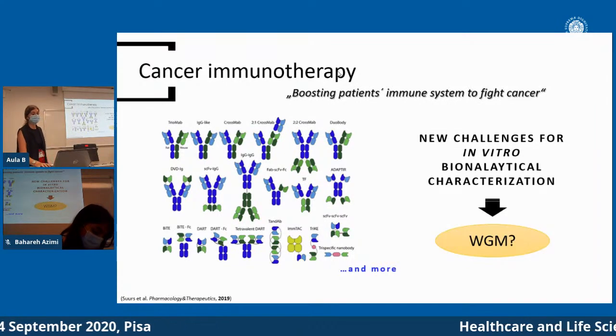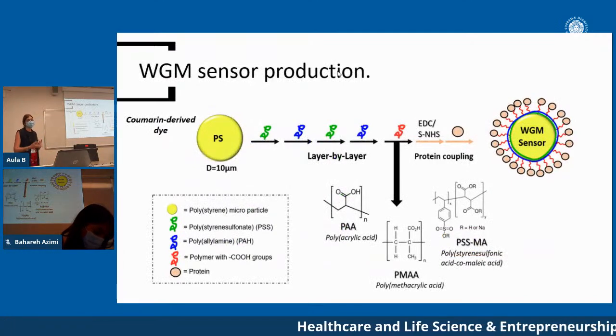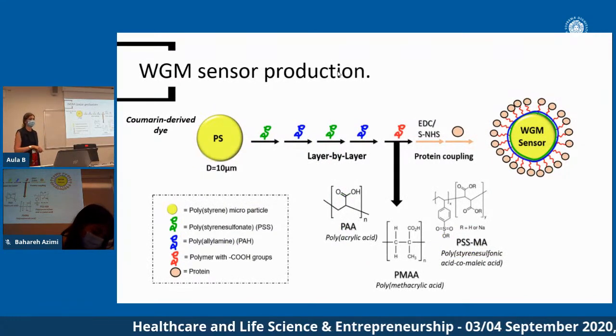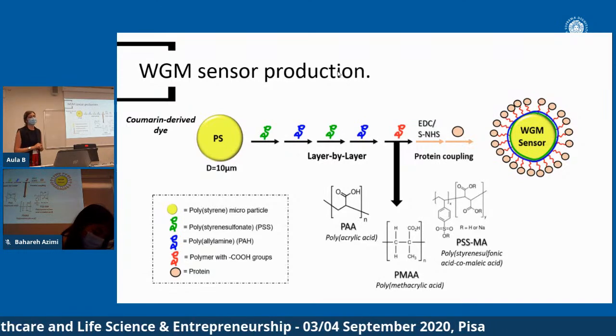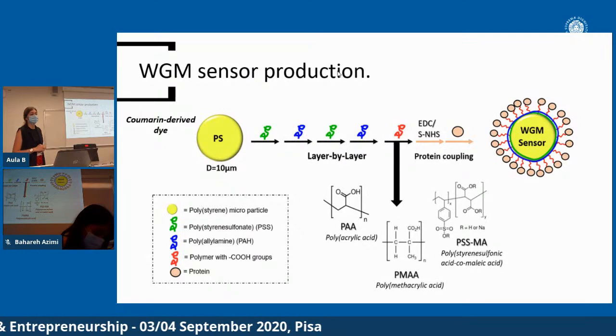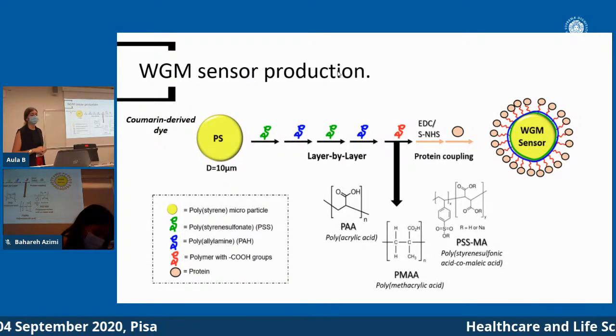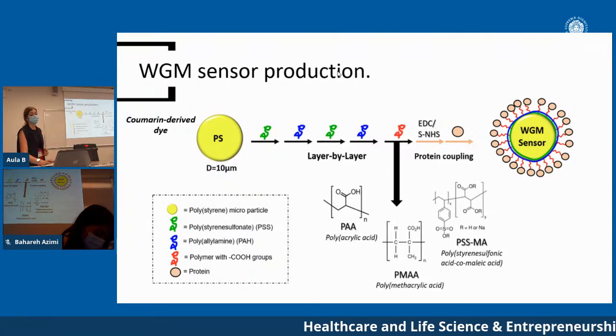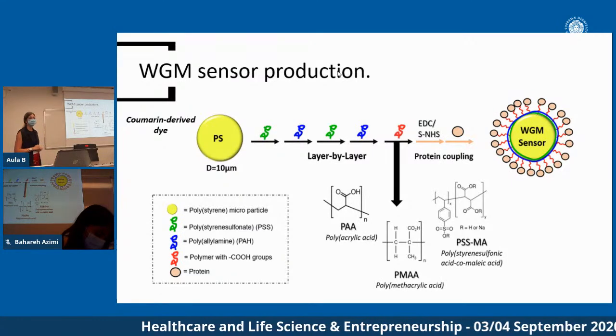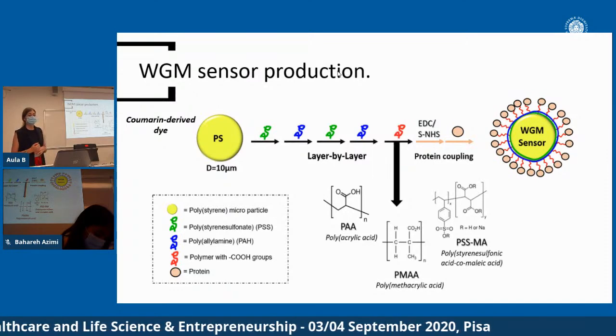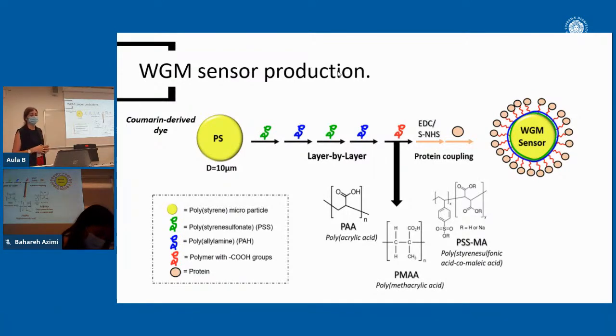to accept this challenge. So first of all, we need to optimize the production of the sensor. Sensors are produced from polystyrene particles of around 10 micrometers, which contain a fluorescent dye. These particles are coated up to 2 bilayers by the layer-by-layer technology with different polyelectrolytes. And we try to optimize this sensor production by evaluating which of these three polymers, polyacrylic acid, polymethacrylic acid, or polystyrene sulfonic acid-co-maleic acid, is the best option for coupling protein on the surface through the